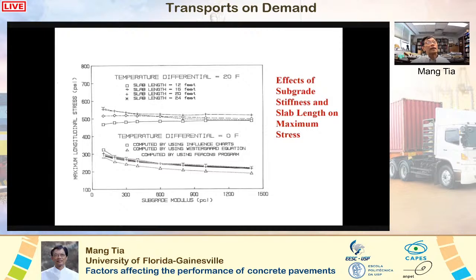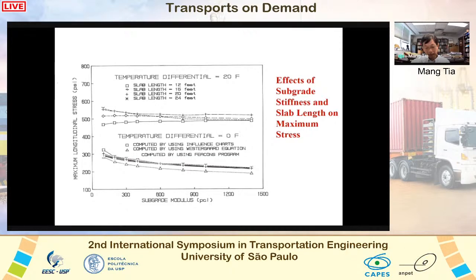Well, when temperature differential in a concrete slab is not considered in stress analysis, as shown by the plots at the bottom of this figure here, the stiffness of the subgrade has a significant effect on the maximum stress. This is a plot of maximum stress versus subgrade stiffness. As the subgrade stiffness gets higher, the stress goes lower, and this is our conventional theory about the effect of subgrade. If you use a stiffer subgrade, the stress would be lower, and that's true if there's no temperature differential. But when temperature differential is considered, the stresses are much higher, but also the subgrade stiffness has less of an effect if temperature differential is considered in the analysis.